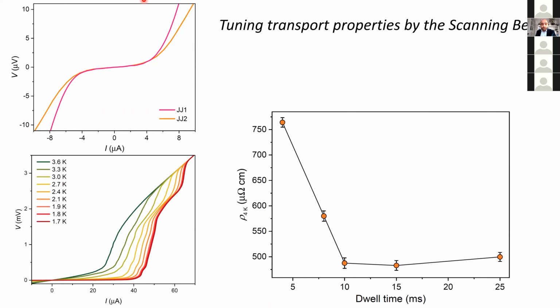And that is because the weak link for this junction was deposited at a slower rate, let's say with a higher dwell time in the EBID language, which means that this weak link has a lower resistivity. And the ones I'm showing in the upper panel are deposited using 4 millisecond dwell time, and therefore they have a higher resistivity, which results in a lower critical current.